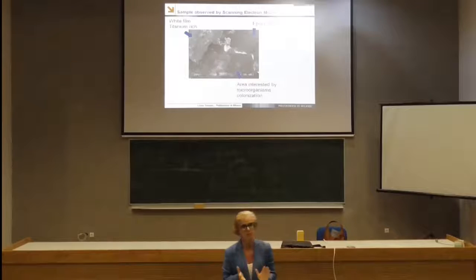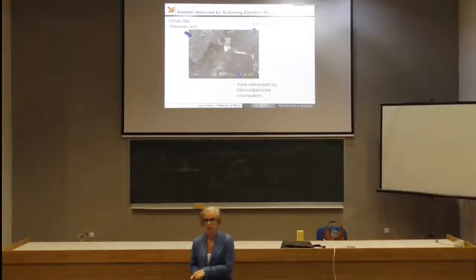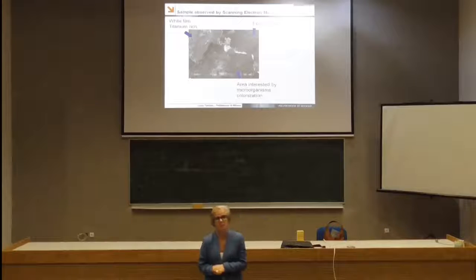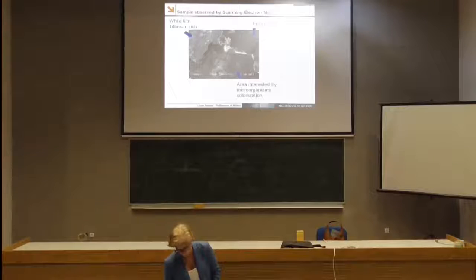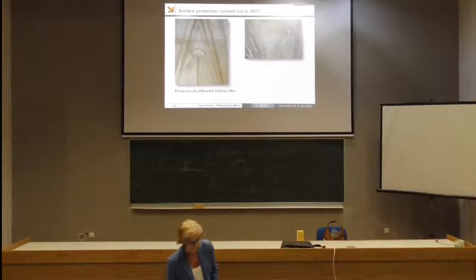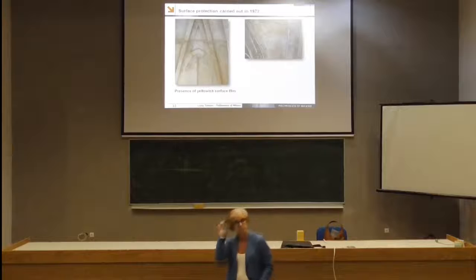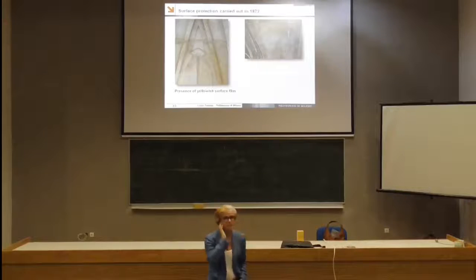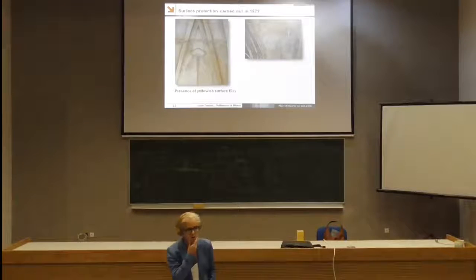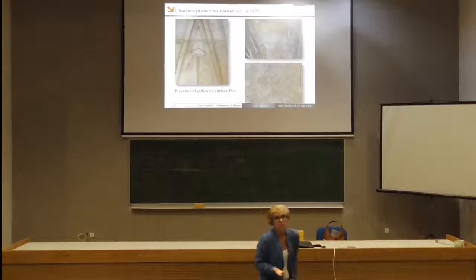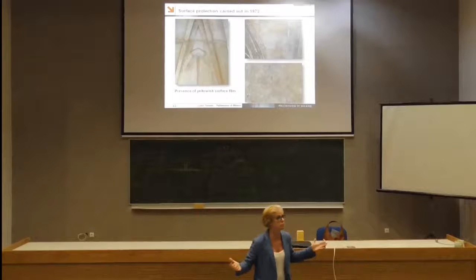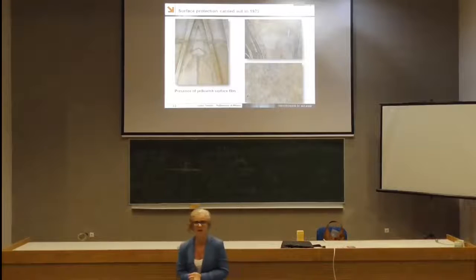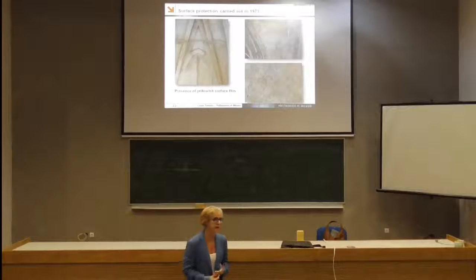So it's important to know that sometimes organic materials that have been applied to conserve some monuments in some specific condition can be the substrate for the growing of biofilms. At the same time, you probably know that many acrylic resins, it's very famous also in Athens, the use of acrylic resin on the monuments, and these acrylic resins have the great defect, but it's normal because there is no material that is able to be durable for decades without any transformation. And these acrylic resins are yellowing a lot and very fast.